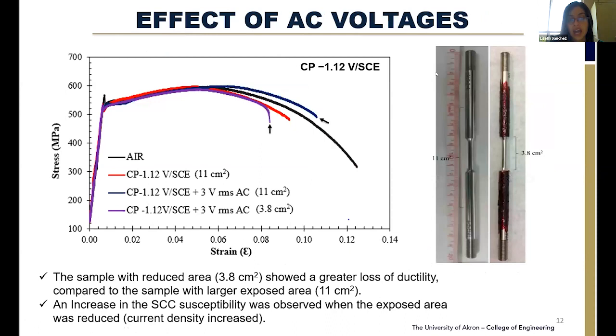I now apply the AC voltage. So this is a result with the cathodic potential that was the most negative, with the AC voltage. In this experiment, we used an area of 11 square centimeters and then I decreased it. I covered some parts of the sample with an epoxy with the idea of only exposing 3.8 square centimeters. With that, we have less area, so we increase the current density going to the sample, and we can see the effect of AC better.